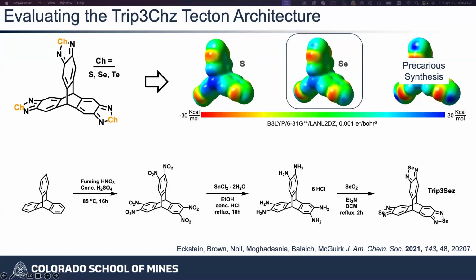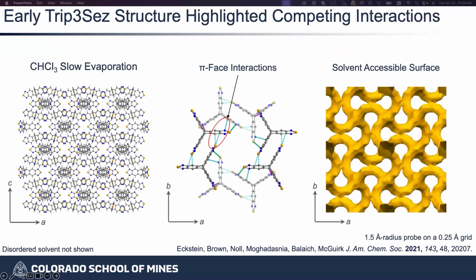Okay, so when we took this molecule, what we wanted was to form one of those honeycomb type structures that I showed at the beginning of this section, where the only thing connecting the molecules in space were interactions between selenium and nitrogen non-covalently. Not even close, all right? So when we crystallize this out of chloroform, these are all single crystal structures. I have my 3 views here, so kind of macro, kind of more local, and then the spaghetti from Mercury, all right? I just like that image. There's no real information out of it. But what we can see here, and one thing I like to always say to students is that there's no such thing as a failed single crystal structure.